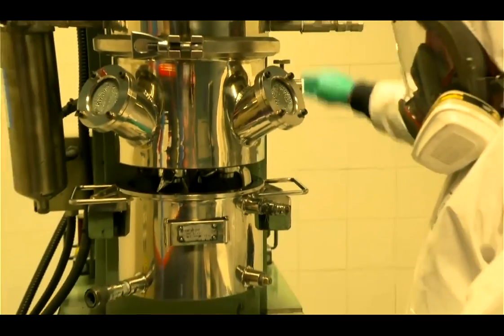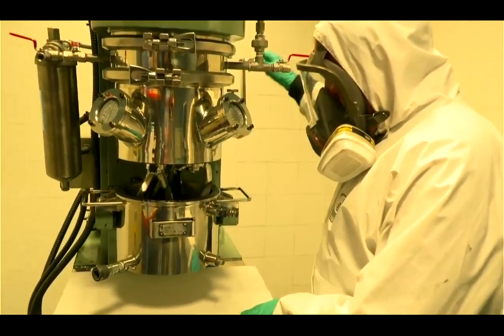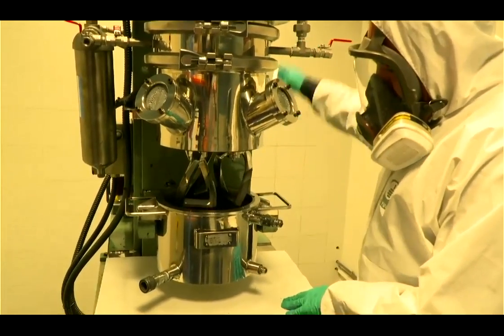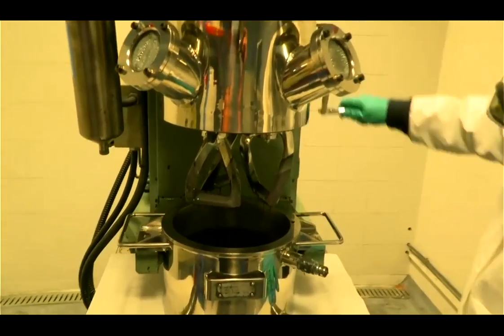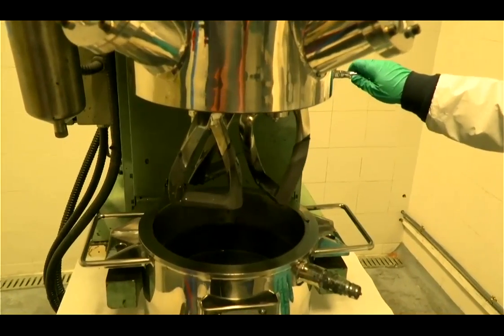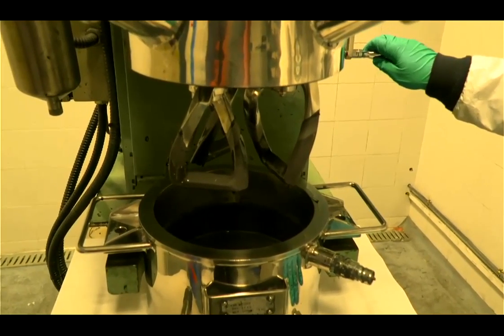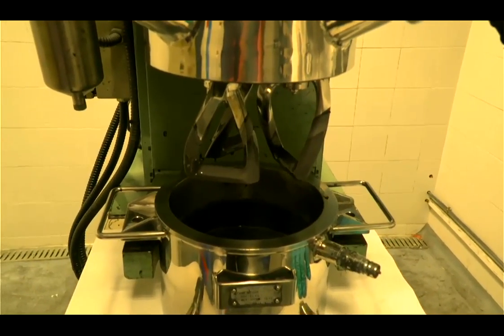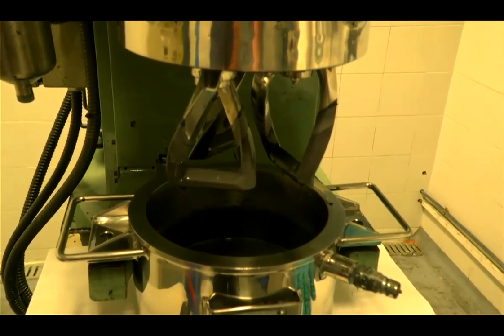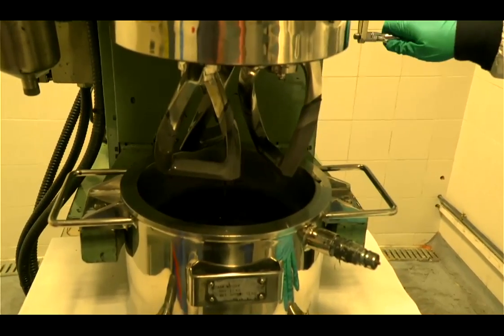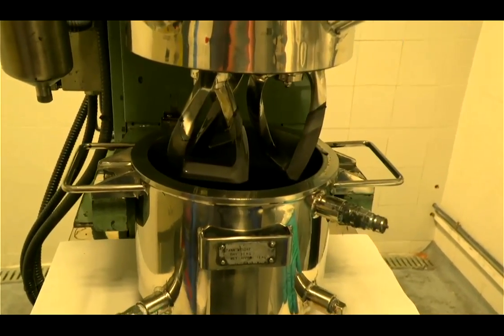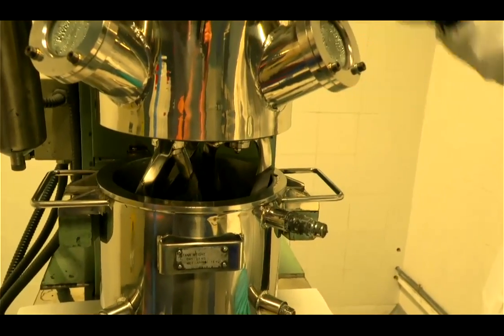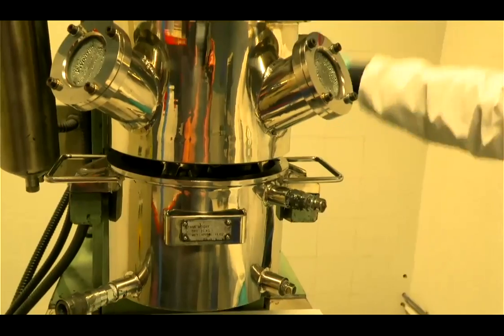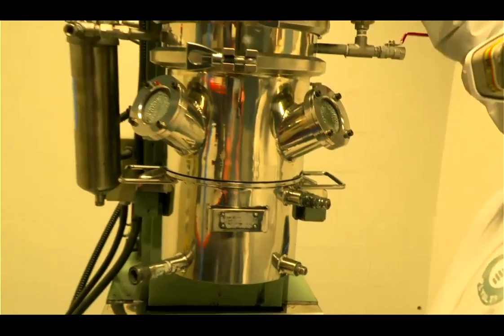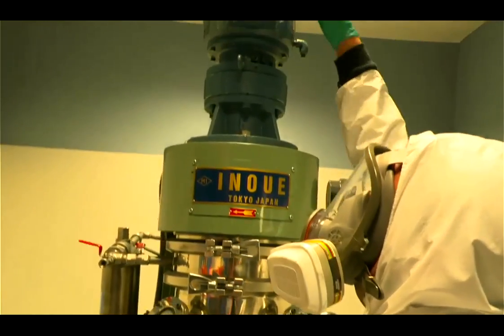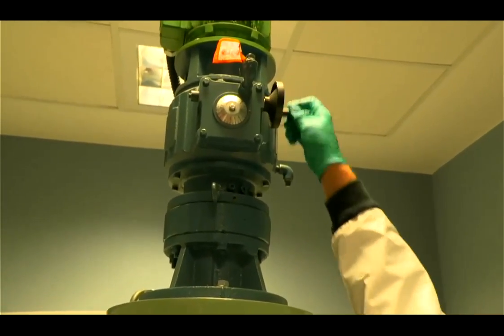Yeah, actually, as Aitor is mentioning, the mixing time will depend a lot on the composition of the electrode. If we have nanoparticles or carbon nanotubes, particles that are very, very small, it's very difficult to make a good dispersion of them. So it will take time first to get the dispersion of these nanoparticles or nanotubes, and after we need to incorporate this dispersion into the slurry. As Aitor said, I would say an average of 4 hours for the preparation of one slurry in the pilot plant. Iker is now showing the mixer.